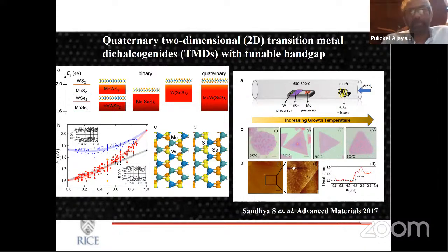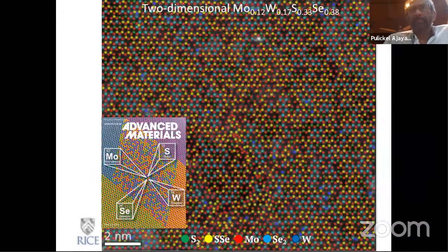So it's always interesting to go to the higher component system. And here is actually a beautiful image from the molybdenum, tungsten, sulfur, selenium alloy, a single layer or single unit thickness of these. And you could see map very nicely the various arrangements of sulfur and selenium in these kind of alloy layers.